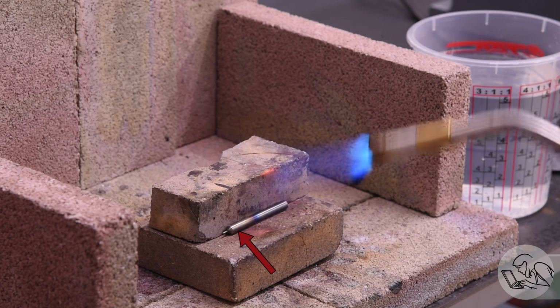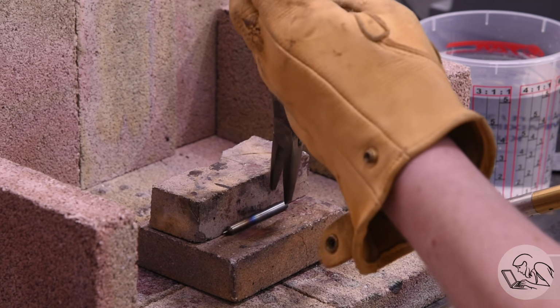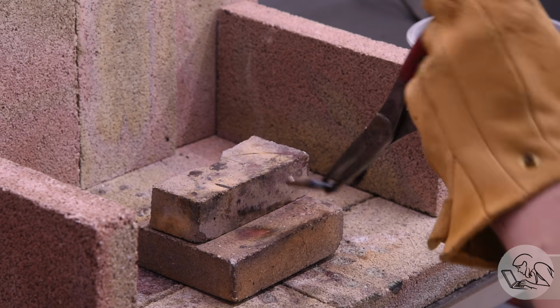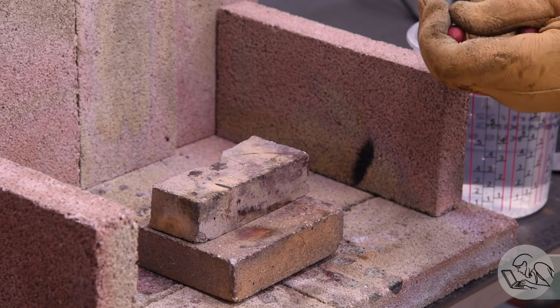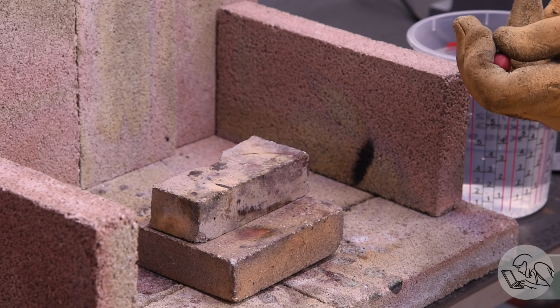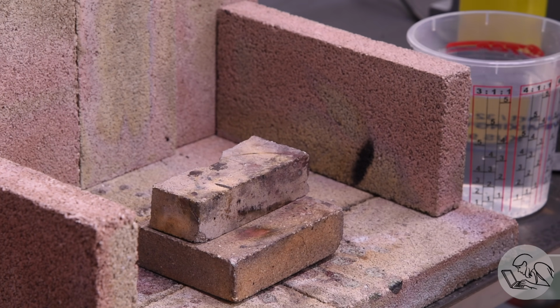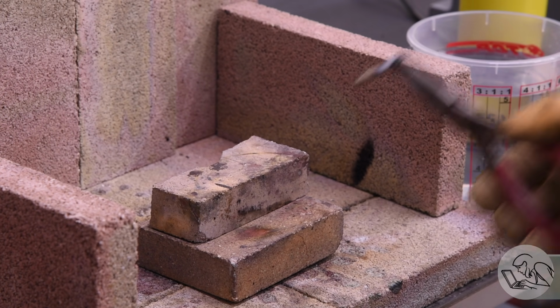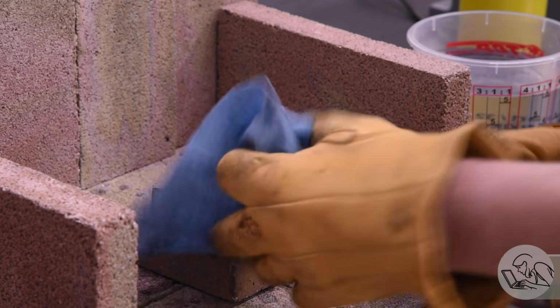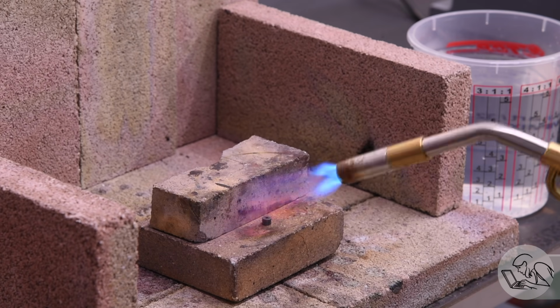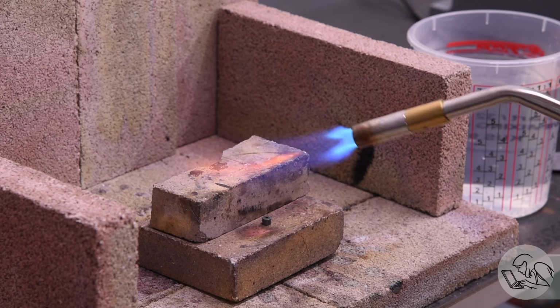Now the trick here is that heat has inertia. So you need to stop tempering a little bit sooner than you think you should and then immediately quench the part in water. Now this quench does not harden anything, this just stops the tempering process. It puts the brakes on that heat inertia. This is the same reason that you rest meat after cooking it, because it keeps cooking after you take it out of the oven. Tempering steel has the same effect.